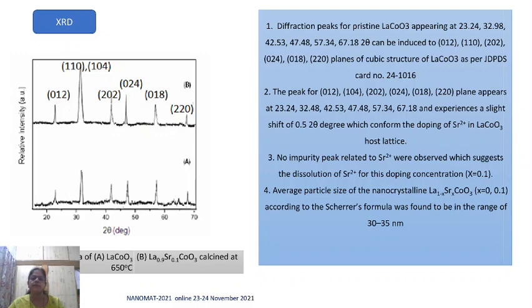No impurity peaks can be observed, which suggests the dissolution of the Sr ion for this doping concentration. The average particle size of the nanocrystalline LaSrCoO3 according to the Scherrer formula was found to be in the range of 30 to 35 nanometer.